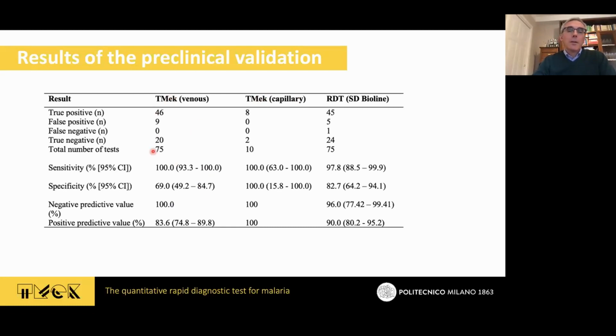So for the venous sampling, we had a number of tests that correspond to 75, and sensitivity was 100%. No false negative, that's very important. And the specificity is about 69%. So we still have some false positives. So if we move now to the capillary, which means we just take a small blood sample from the finger of the patient, we found that the number here is very limited in terms of samples, just 10, but sensitivity is 100%, specificity very high. The confidence intervals are very wide due to the low number of samples, but very promising.